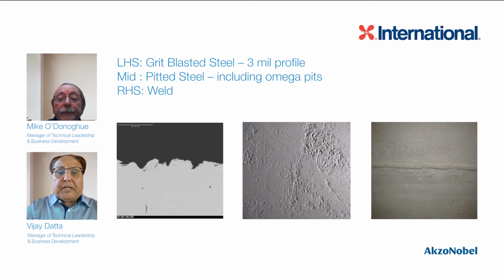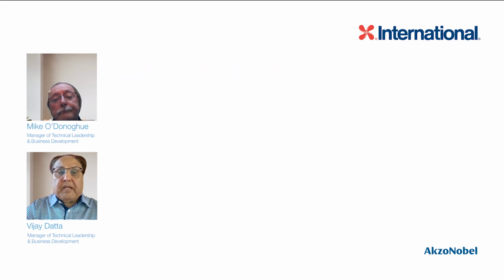The middle picture here is the pitted steel, including some of the omega pits, and the purpose is to really clean these pits before we can apply the coatings. And the right-hand side is a typical weld. As you can see, there is also pitting around the weld areas, and that also has to be prepared properly when we apply these coatings.